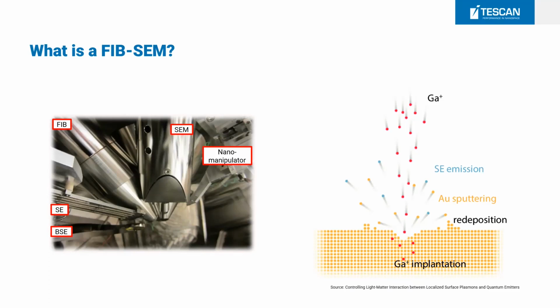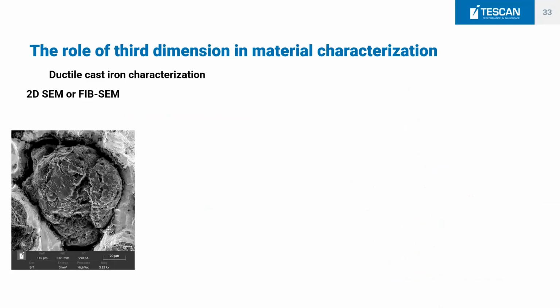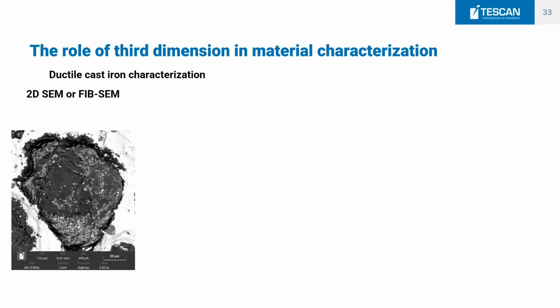And through that, we remove the surface of the material, but not randomly. We're really scanning across a small area of interest at the nanoscale. So our spot size is a couple of nanometers big. And therefore, it enables us to cut very small cross sections at specific areas of interest. And it emits secondary electrons, but it also sputters out the original material. Yeah, there are some implantation and redeposition, but in general, you can really mill through the material wherever you like, which is all great.